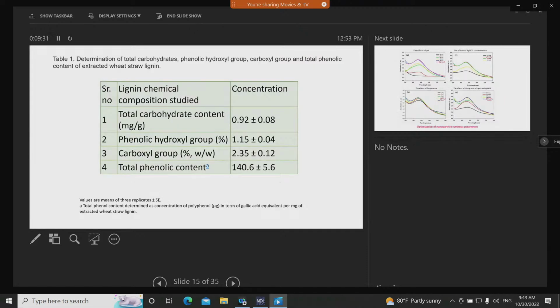Here we have determined the total carbohydrate content, phenolic hydroxyl groups, carboxyl groups, and the total phenolic content from the extracted wheat straw lignin, in which we can see the total phenolic content is found to be higher compared to the other lignin chemical compositions studied.